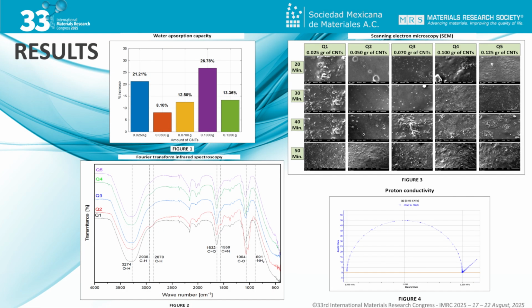Results: when analyzing the water absorption capacity of the 5 membranes tested, it was found that the membrane with 0.050 grams of carbon nanotubes presented the highest resistance to liquid absorption, as shown in Figure 1. This led to the discovery that membrane Q2, when operating in a fuel cell at 80 degrees Celsius, exhibited the highest proton conductivity of 2 times 10 to the minus 2 Siemens per centimeter to the minus 1, as shown in Figure 4, which is 1.5 times higher than a membrane without carbon nanotubes.